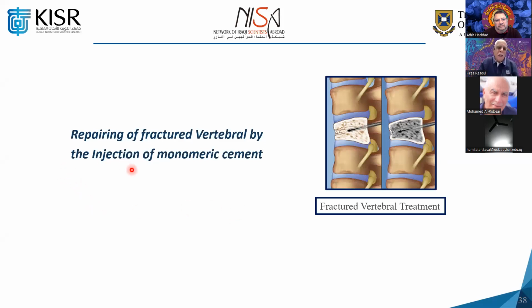So the typical curing, they try to inject monomeric cement. And typically what they inject is methyl methacrylate. Methyl methacrylate has very, very low viscosity. It's like water. And plus, it is very, very toxic. But whether you have the pain or you accept some small toxic material, which might probably cause some issue, it will disappear after the polymer cures.